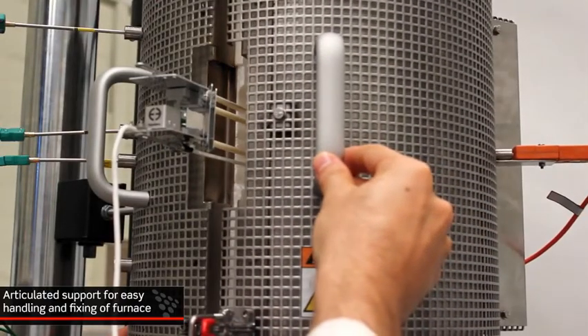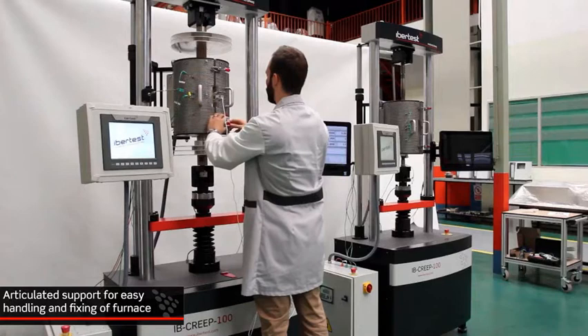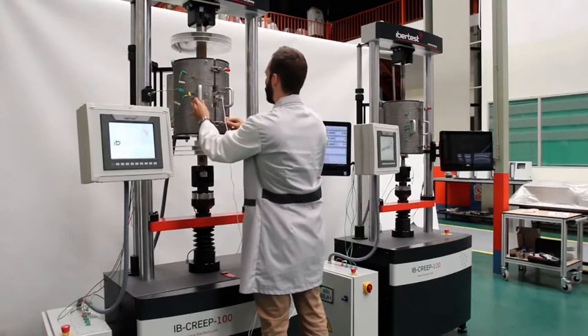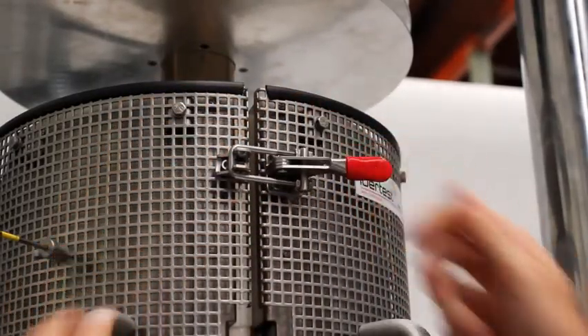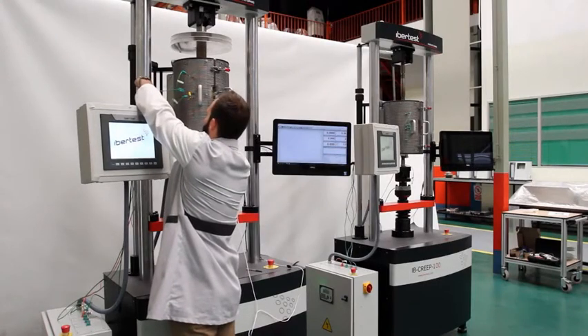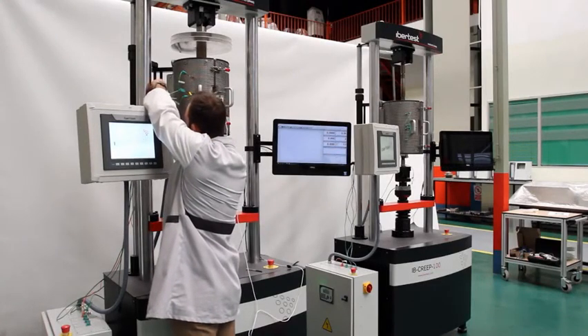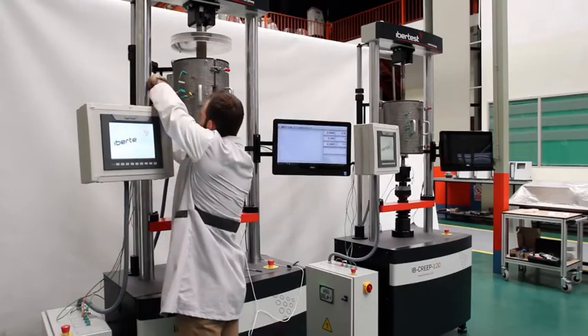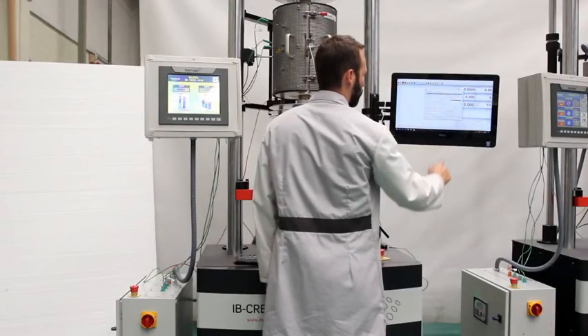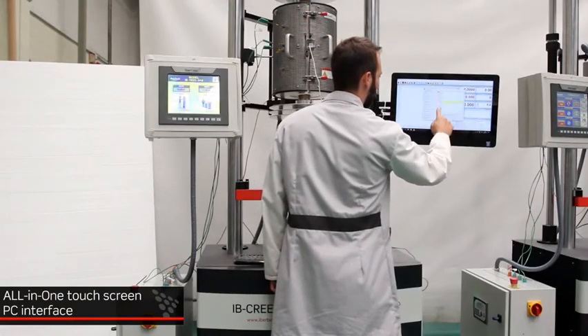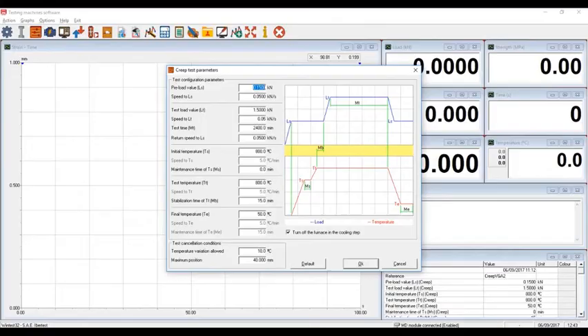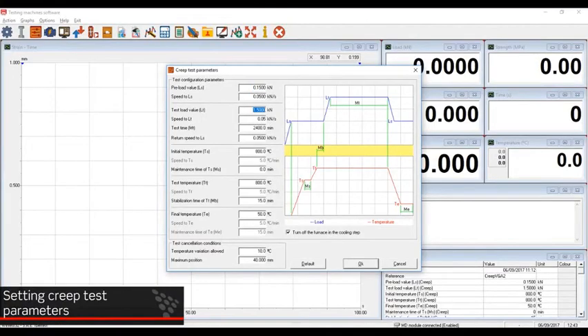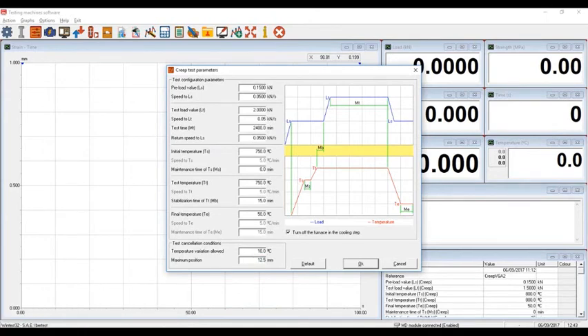And you close the furnace, and then you have to apply a little amount of preload. If there is any thread which is missing or loose, or any misalignment, that should be taken care of by application of a very small amount of load. And whatever displacement happens, you make it zero by doing zero correction. So you just set it to have a value of zero. In this case, you see there is 0.15 kilonewton of force applied, which is a preload, and then the test load value is 2 kilonewton.